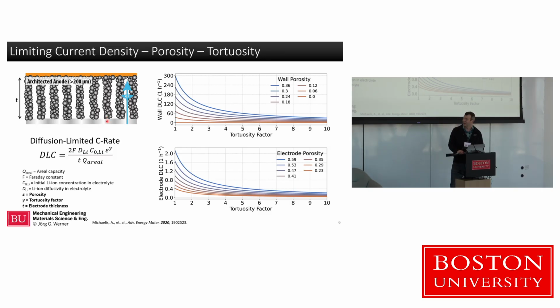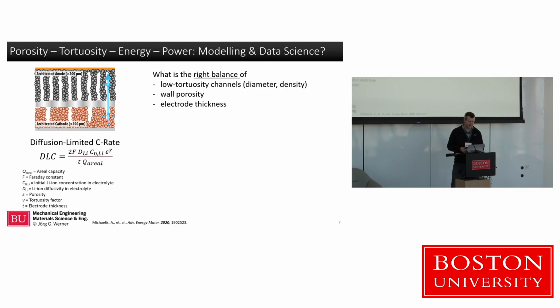Now, this is an equation that has some backing to it, but it may not necessarily directly correlate to what we observe experimentally, and I'll show you that later as well. In any case, when we look at that, the questions we should ask is, what's the right balance of low tortuosity pores, let's say these channels that we architected here? What about the porosity within the wall? Can we push these together, make like 5% porosity, and we're good to go? And how does that correlate to the electrode thickness?